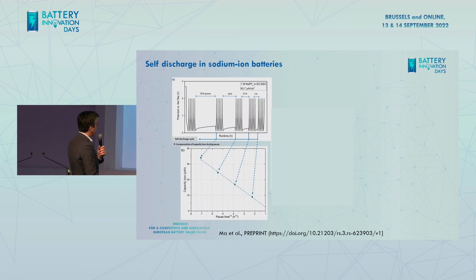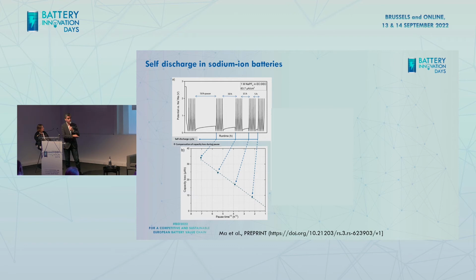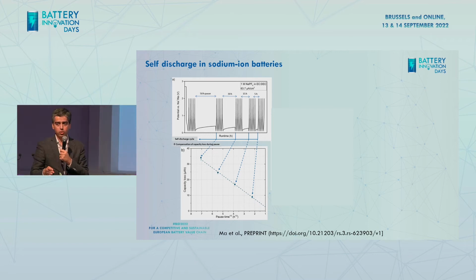What we do is cycle a sodium-ion battery, as everyone does, but we make an extended pause between cycles. You can see that there is a long pause time after 5 cycles, and you can see that the time of this pause is changed.